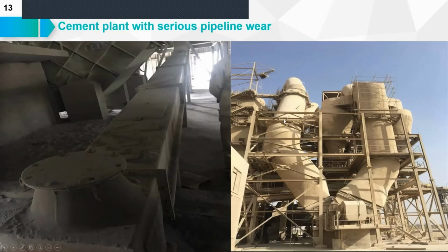Then I saw the technicians make a weld with steel to cover the hole. After a few months they do the same again, waiting for the next downtime maintenance, until the pipe has been welded so much that you have to cut all the pipe, redesign, reconstruct, and stop and wait. This becomes a big project. So why don't we solve this problem fundamentally from the beginning, just by applying wear-resistant ceramic coating materials?